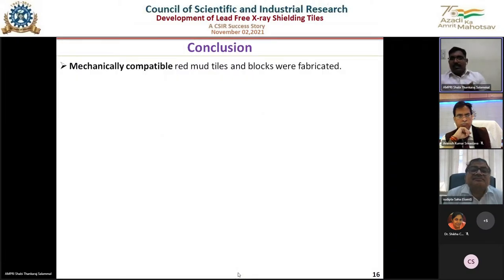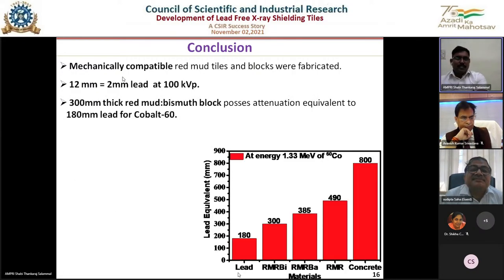So we have made mechanically compatible red mud tiles as well as blocks. And a 12 mm thick tile possesses attenuation equal to 2 mm lead. And a 300 mm thick red mud bismuth block is sufficient to build a radiation shielding structure for cobalt-60.